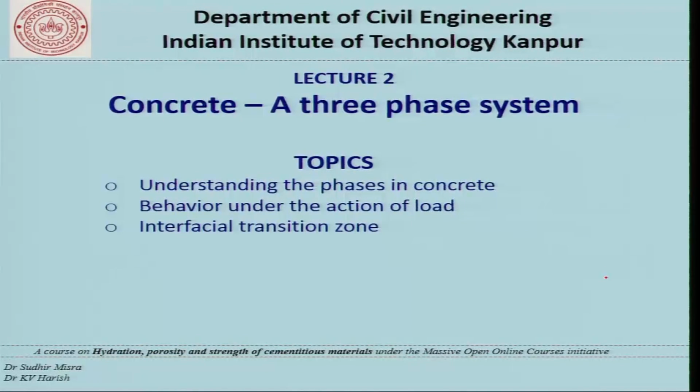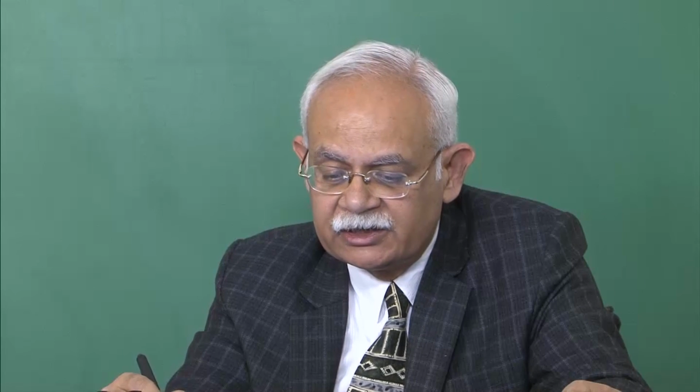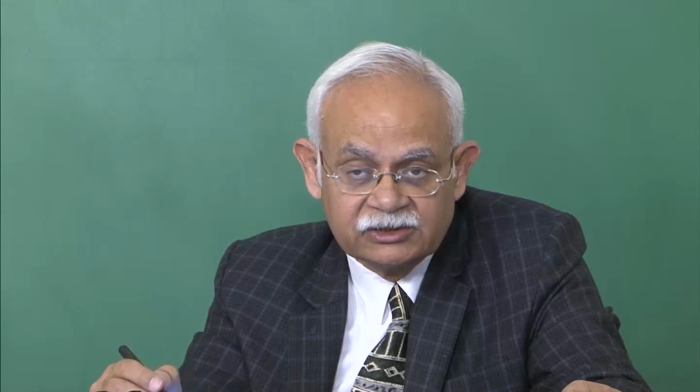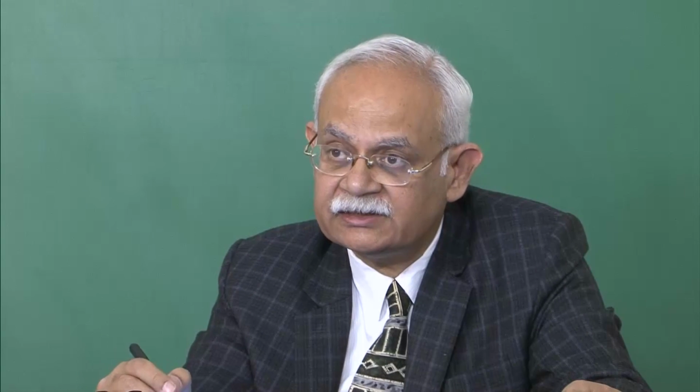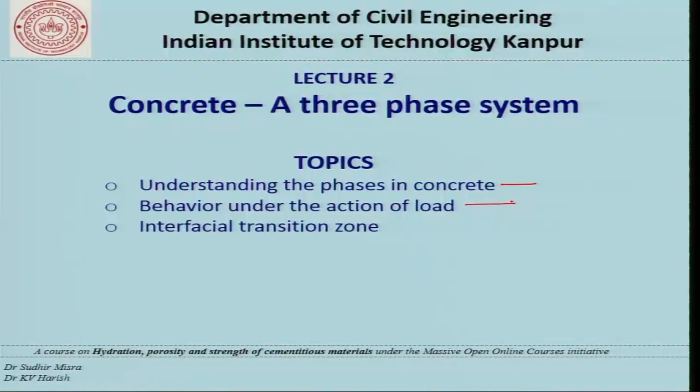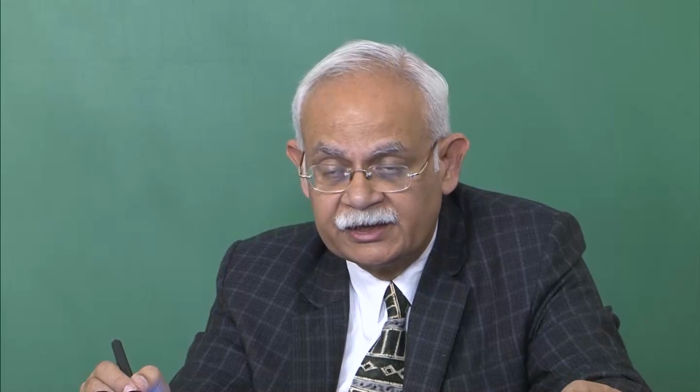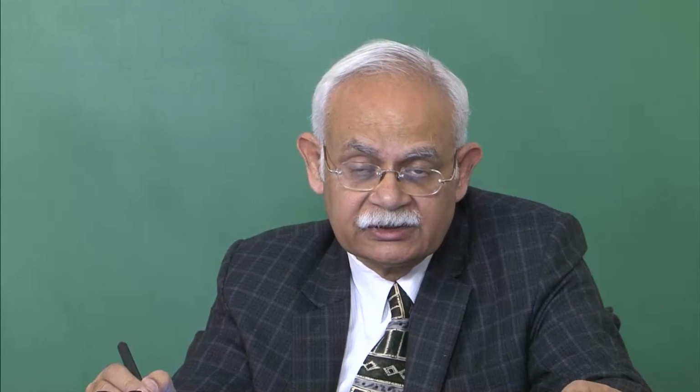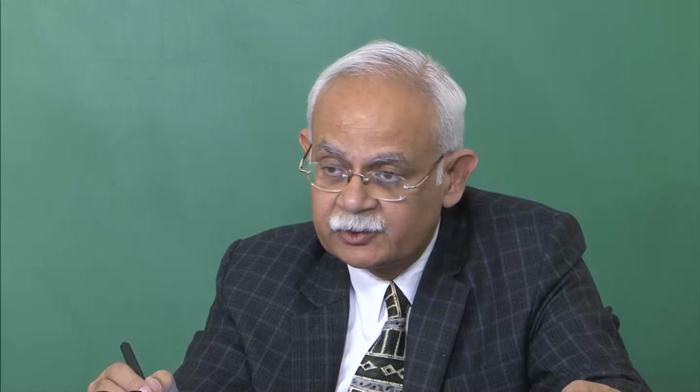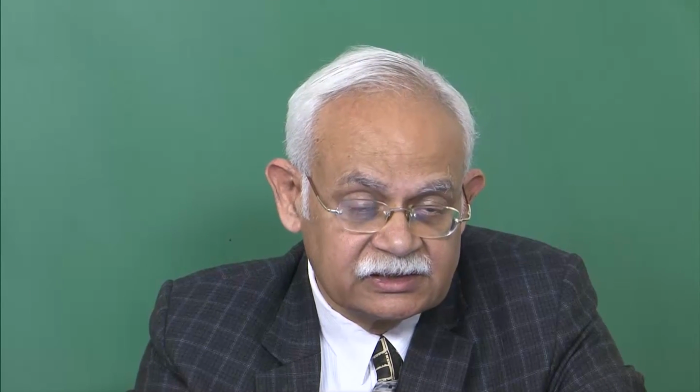So with this, what we did today was try to understand the phases of concrete, that is the coarse aggregate, mortar, and the ITZ. We tried to look at the action of concrete under the load if the two phases were taken in series or the two phases were taken in parallel, and argued that so long as the phases were in series, the ITZ has limited role to play as far as strength is concerned, but it will of course have the same amount of impact as far as durability and material transport is concerned.